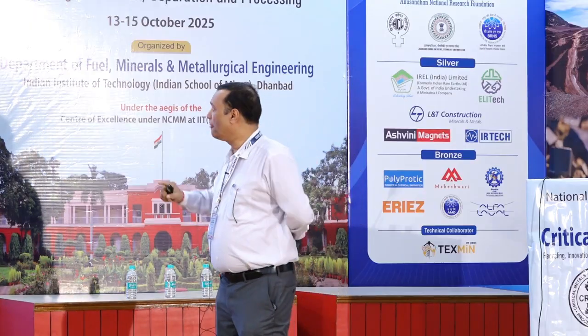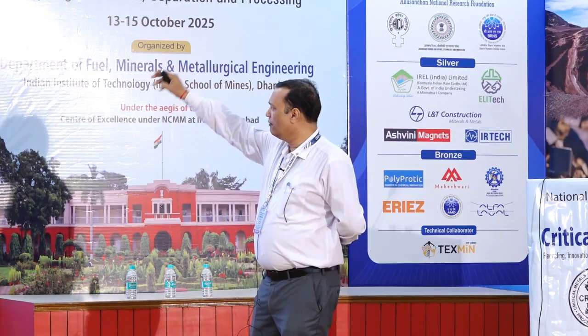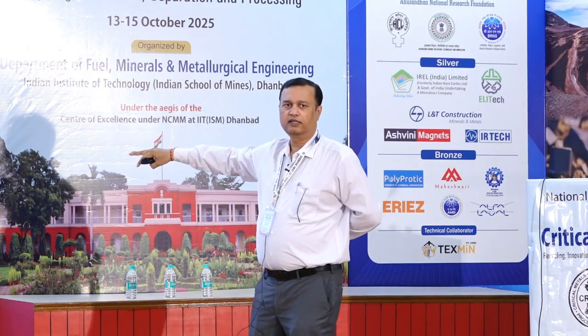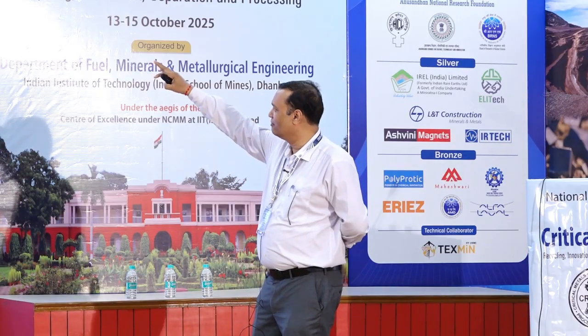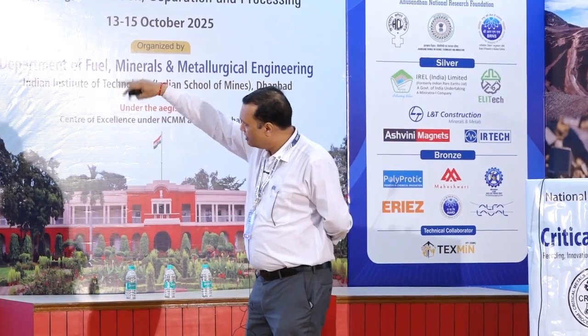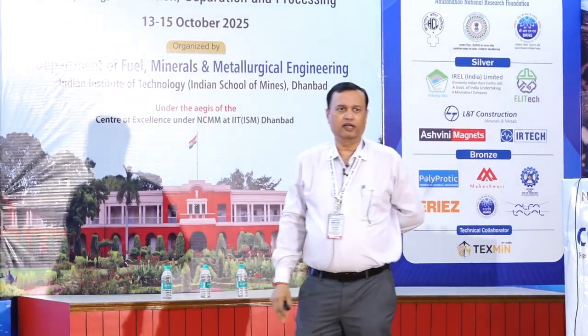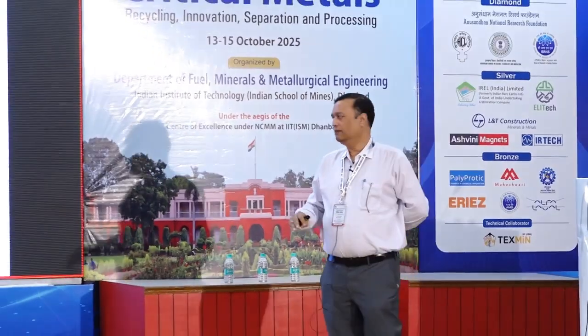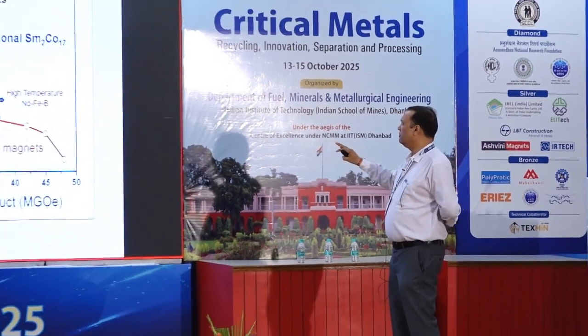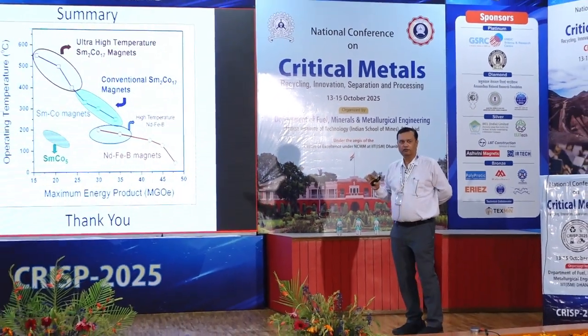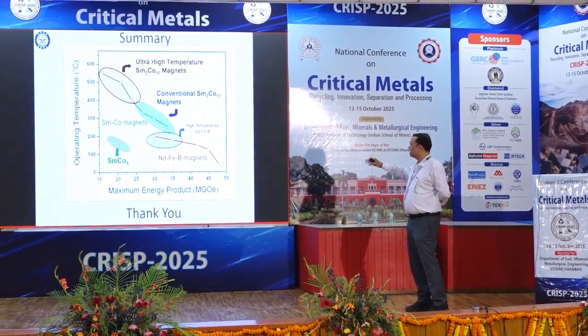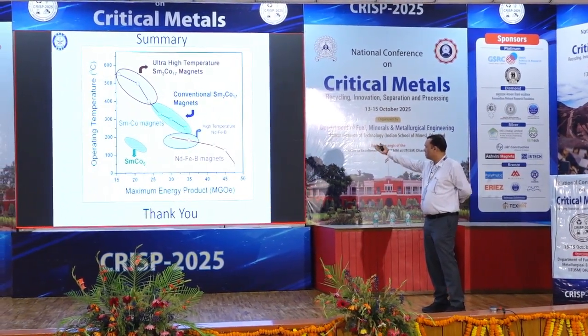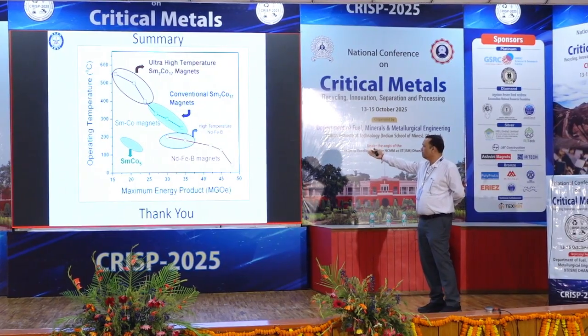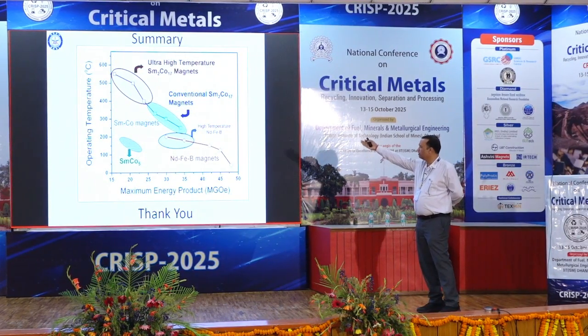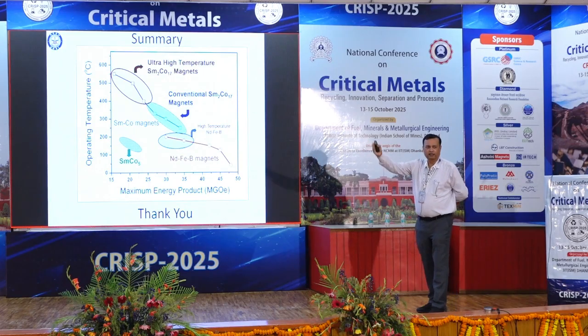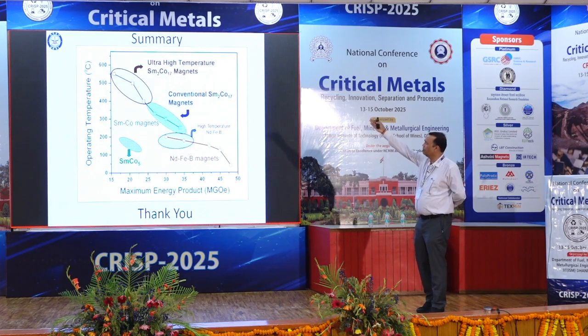So to summarize, I have plotted room temperature energy product as a function of operating temperature. The circle ones are the magnets which we have already developed at DMR, and ideally we see that when we try to increase the operating temperature of a magnet, the energy product decreases. Say NdFeB magnets have around 50 energy product, but when we try to increase the operating temperature to 200, the energy product decreases. Similarly, it happens for 2:17 also.